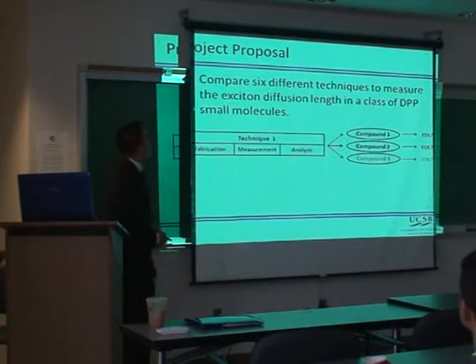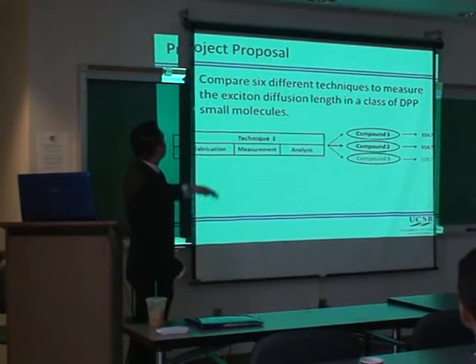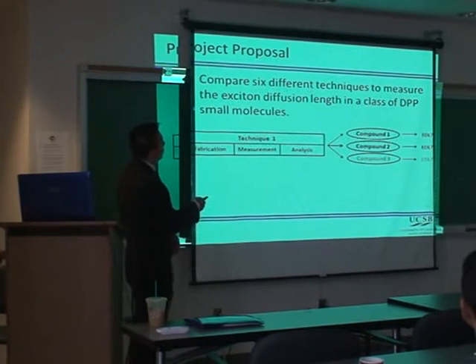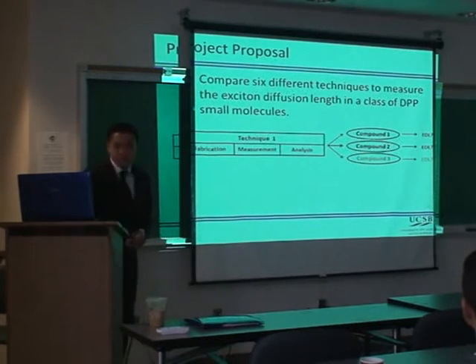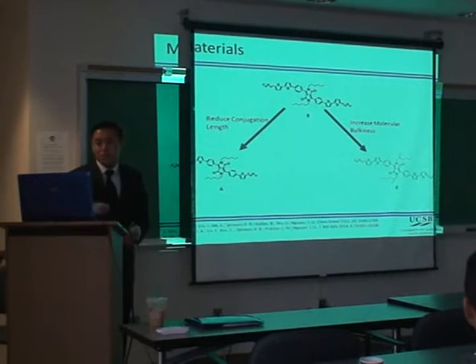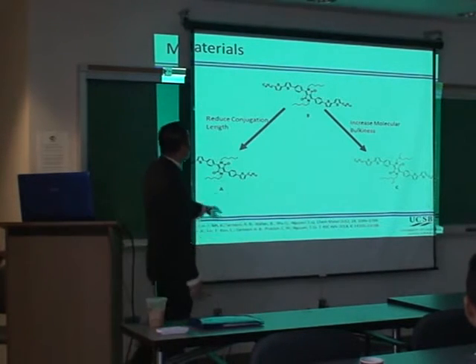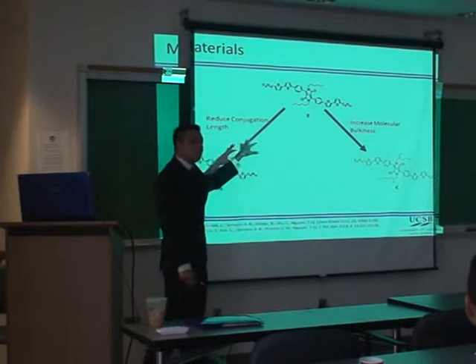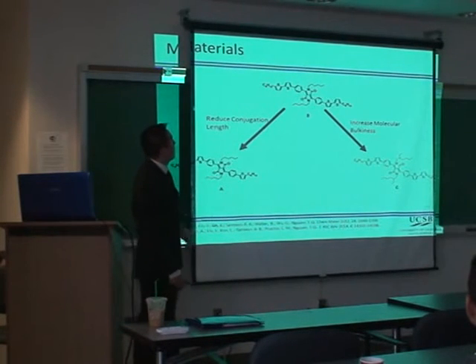So with that, I developed a project proposal, and it's to compare 6 different techniques to measure exciton diffusion length in a class of diketopyrrolopyrrole small molecules. So the first choice was what material I would use. So I chose these 3 small molecules because they have very slight but interesting chemical modifications.